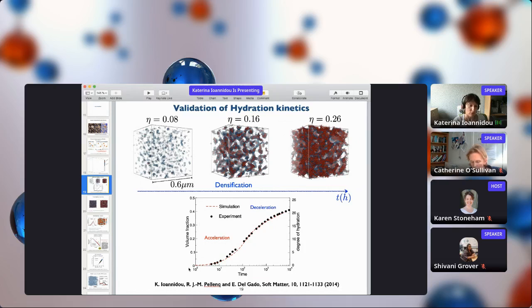So we're able to compute the increase of the volume fraction with time and compare it with the degree of hydration. We observe an accelerating and decelerating regime, giving this typical sigmoid curve that we see in different growth phenomena.